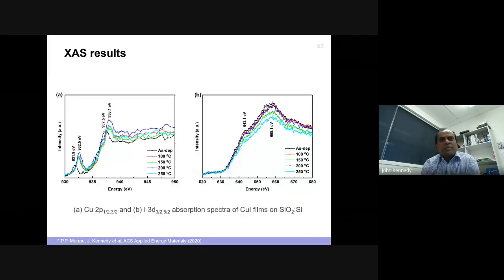Then we used synchrotron XAS studies, X-ray absorption studies, to look at the copper 2p states and 3d states, to see whether these precipitates are visible or whether you have some sort of density of states, defect states basically. The pre-edge features of copper 2p suggest copper metal like a defect state, and the shift of the transition peaks in the annealed films indicated that there is a definite structural difference.